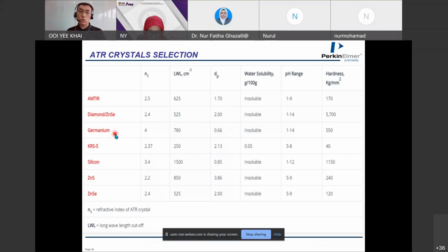So germanium is good for dark-colored samples or samples that tend to absorb a lot of IR, for example graphite, graphene, or CNT, carbon nanotubes. But the trade-off is it only scans down to 780 wavenumbers. That means below this, you will only get noise. And germanium is fully metal, so you do not run acid or base or highly ionic, highly ionizable species, because it will react. Zinc selenide is good for oil samples and petrochemical applications generally.